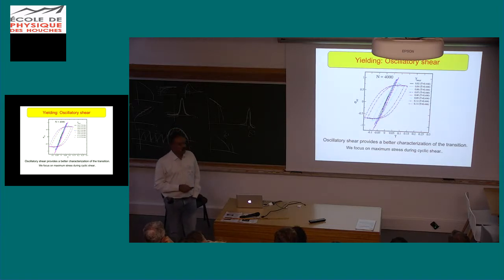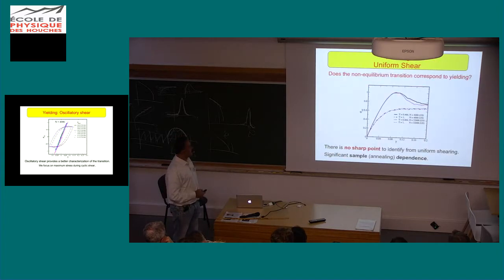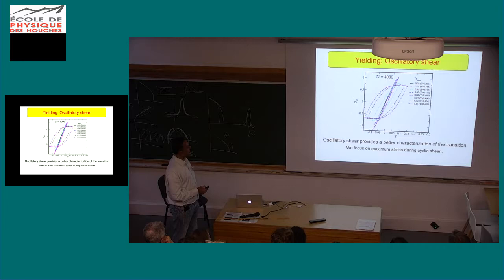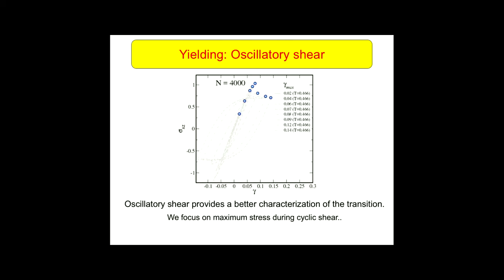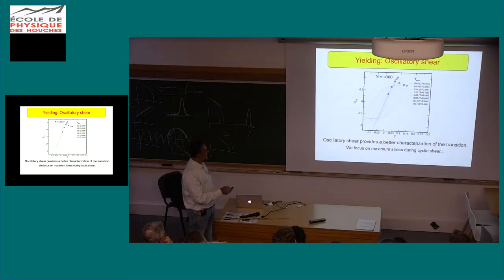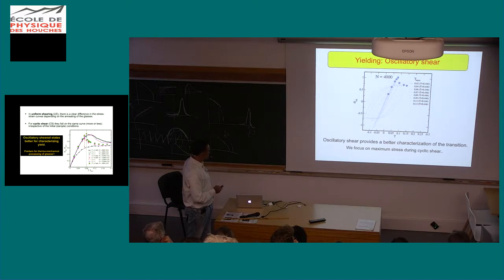And here, in order to make a similar graph as this, we will look at the maximum stress that is achieved for any given strain amplitude, and those points look like this. And what you see is clearly a sudden drop in the maximum stress value across what turns out to be the same threshold amplitude of strain. These points could in principle be lower. We just don't get there because, as I mentioned already, the time taken to reach these asymptotic states gets larger and larger as we are close to this transition.